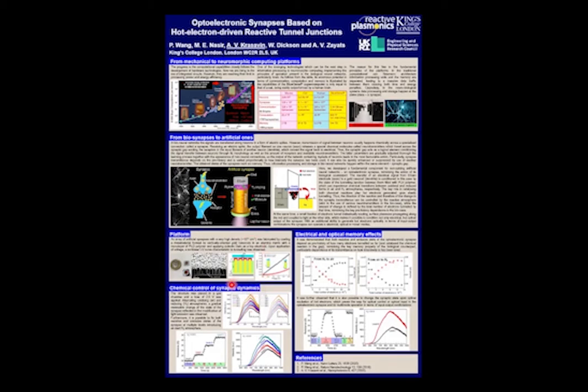And actually, that's what we observed in this experiment. We put our system in reducing or oxidizing atmosphere, and we saw that we changed the weight coefficient for the light emission, and so it is weight coefficient for the tunneling as well, because these two things are related.